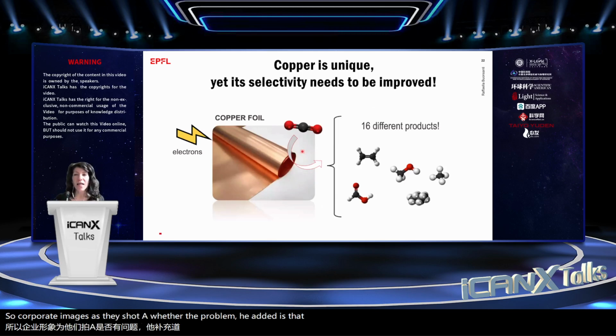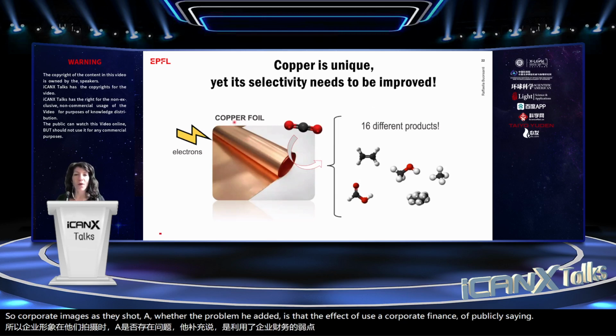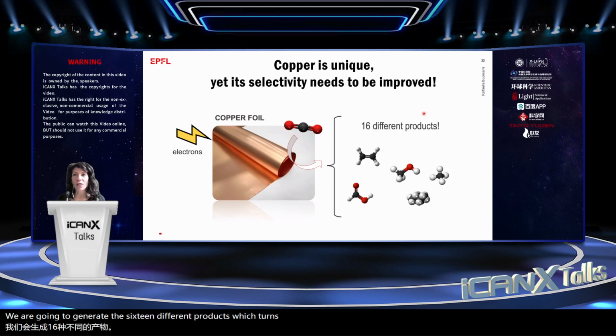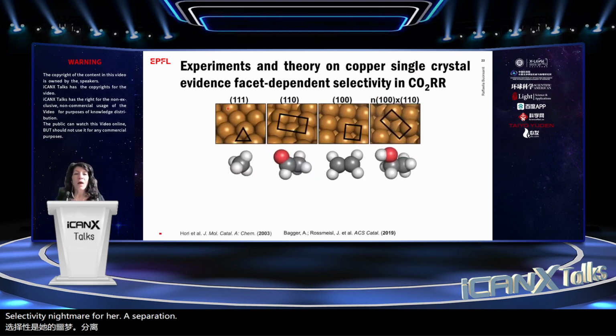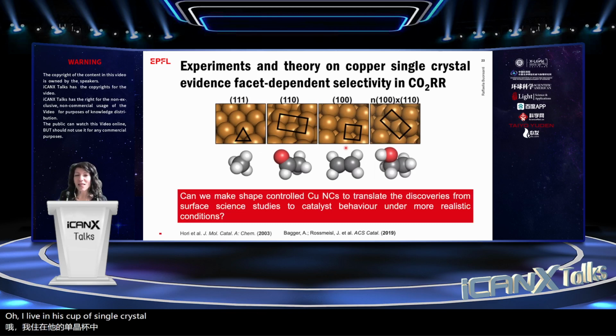However, the problem here is that if we use a copper foil, so polycrystalline foil, we are going to generate 16 different products, which turns into a selectivity nightmare for separation. Now, studies on single crystals by the now famous Japanese researcher Hori evidenced that there is a facet-dependent selectivity of this reaction. In particular, depending on the atomic arrangement of the copper atoms on the surface, the copper can be made more selective, for example, for methane if we expose the 111 surface, or for ethylene if we expose the 100 surface. However, these copper single crystals cannot be utilized in actual electrochemical devices, at the high current density